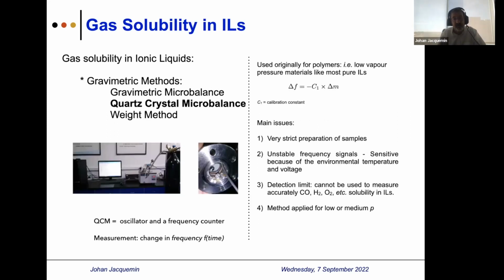For the quartz crystal microbalance, basically what we are looking at, we are looking at the QCM as an oscillator, and we need a frequency counter. And what we are measuring is a frequency change over time. And the solubility can be determined thanks to the formal equation where C1 is a calibration constant, which must be set at the beginning of each measurement with an empty cell, with the gas that you want to set.